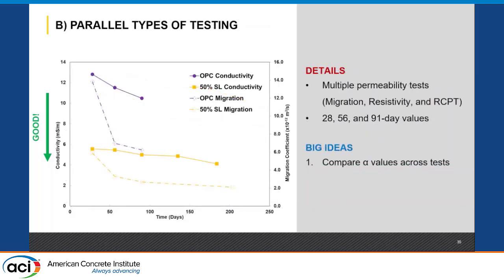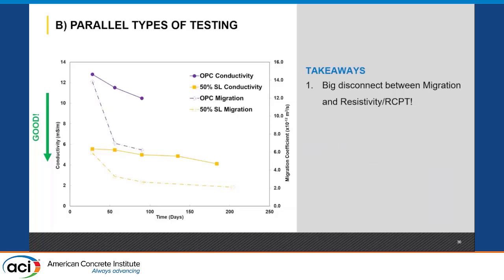The other idea was that we were going to do a bunch of different testing, migration, resistivity, and RCPT, and compare 3 different types of alphas with these. We found a big disconnect between migration and resistivity. You see these are 2 axes, conductivity on the left, migration on the right. And because they're measuring permeability, they should be sort of on the same line or showing the same trend, but yet they don't. We have this huge discrepancy where migration is actually showing that OPC is pozzolanic. That's this big drop right here.